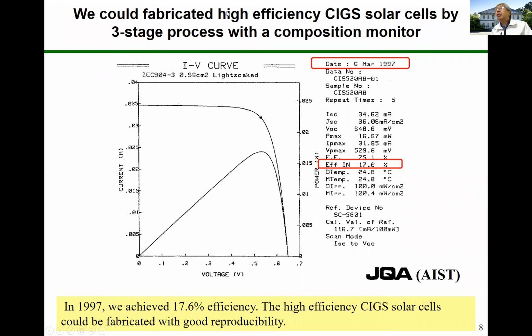We could fabricate high-efficiency CIGS solar cells by the three-stage process and composition monitor. In 1997, we achieved 17.6% efficiency. The high-efficiency CIGS solar cells could be fabricated with good reproducibility.